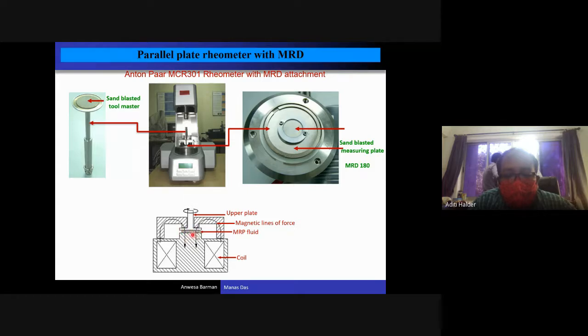In between these two plates, MR fluid is kept. The plate is 20 millimeter in diameter and the gap thickness is 1 millimeter. The MRD device has an electromagnet, so the magnetic field is applied perpendicular to the MR fluid. The tool master rotates with a certain RPM, and this RPM is proportional to the shear rate. When you apply the magnetic field, there is a resisting torque, which can be measured by the tool master itself. This resisting torque is proportional to the shear stress.